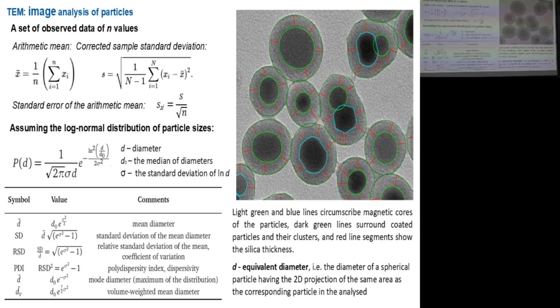Nevertheless, you may like to do some assumption about the shape of the distribution. So typically, the growth of nanoparticles is leading to the log normal distribution, but this is like the most simple situation. It is not valid universally, but it's very common. So you may apply some assumption like this. Again, there are different formulations of the log normal distribution. You can see different expressions here. There might be a natural logarithm of some sigma, and there is also some confusion arising around this. So I would like to make this clear.